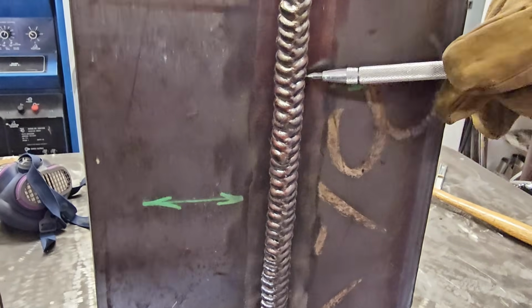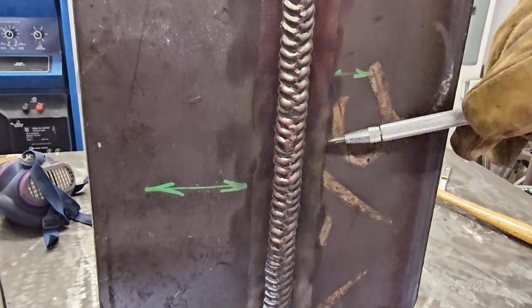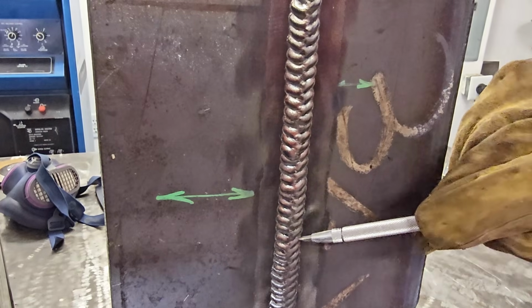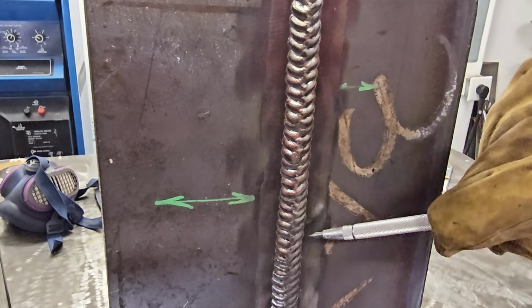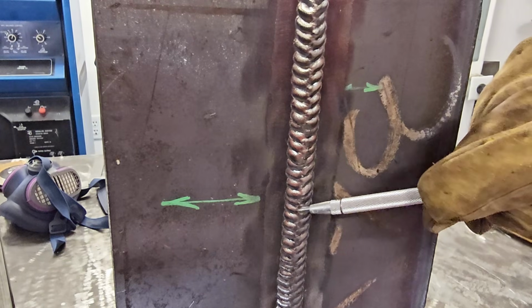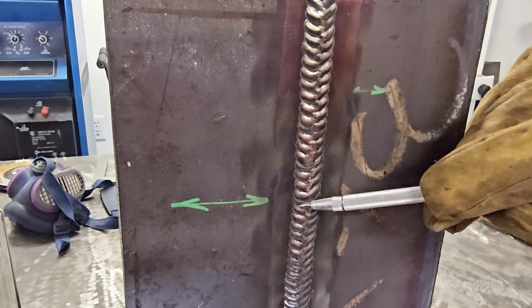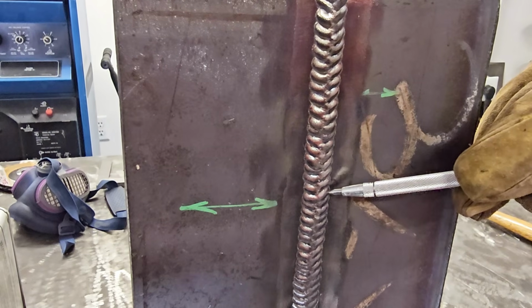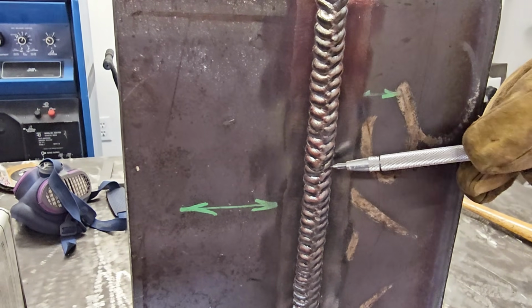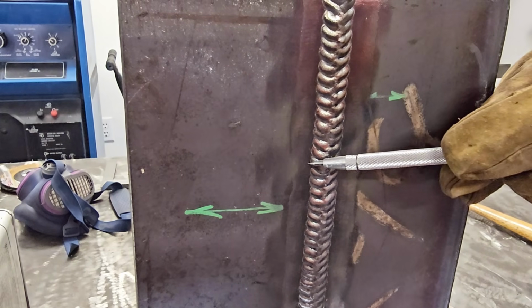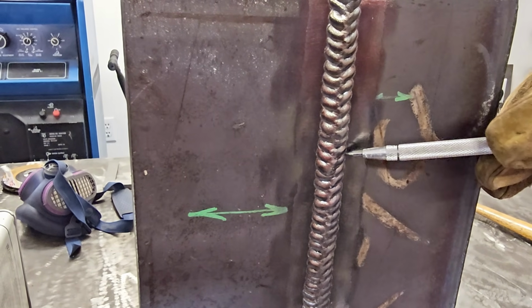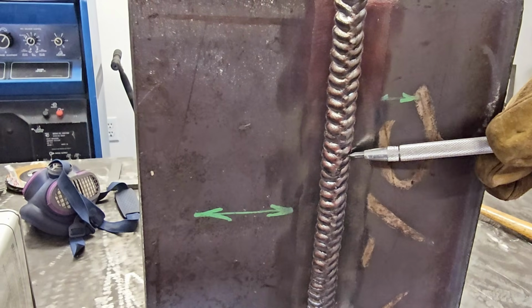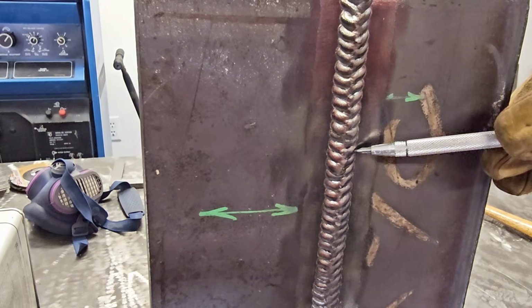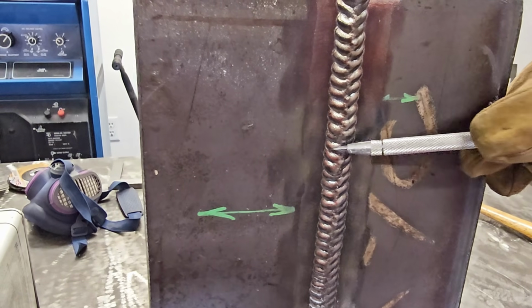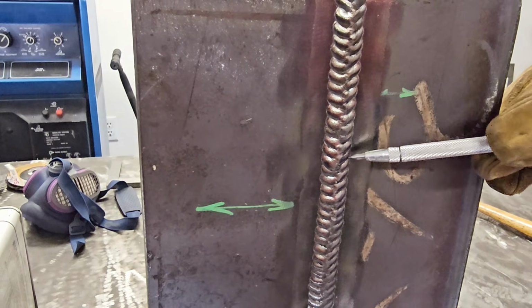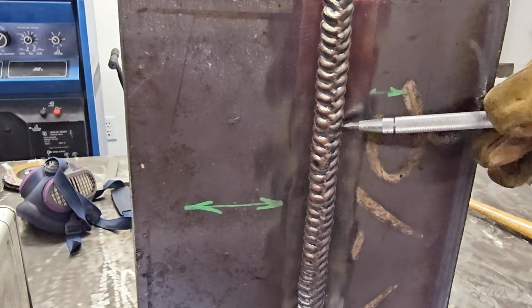So on this cap pass, our maximum height is 1/8 of an inch. So this all looks good in terms of our height. One thing to put into your technique in order to get a nice flat cap pass like this is to go fairly quickly but smoothly across the front of the bead and then pause on the sides. It's really important to pause on those sides long enough to fill any undercut. That way it smooths out the reinforcement all the way across the face rather than having a high center and low edges. So that way it's nice and smooth.